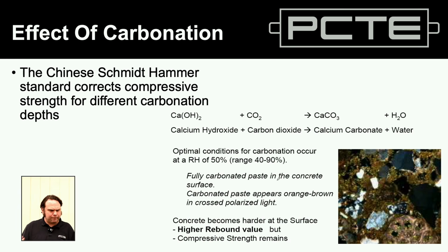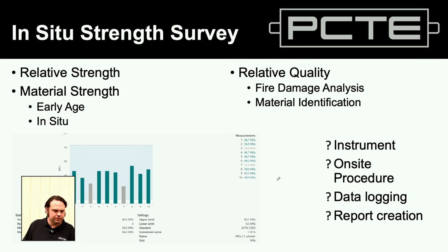And there's a kind of, some of the Chinese standards look at conversions based on depth. There's also a procedure in the system manual and an option to use a correction factor. The intent being you test carbonated concrete and you cut or grind or sample down to uncarbonated concrete of the same type in the same place, and you get the ratio between them. So those are your options for carbonation. As always, it's mainly a concern for very old or especially exposed structures. So road infrastructure maybe would have additional carbon dioxide load, or if it's been there a long time.